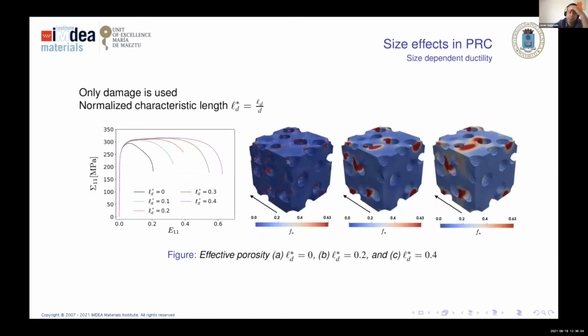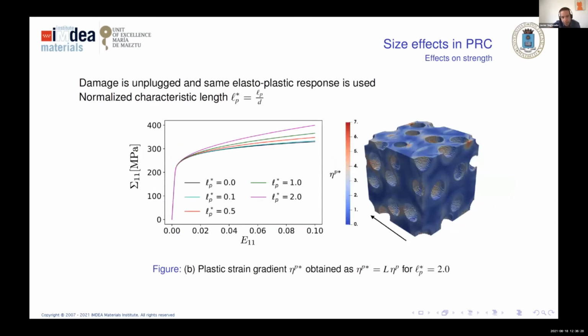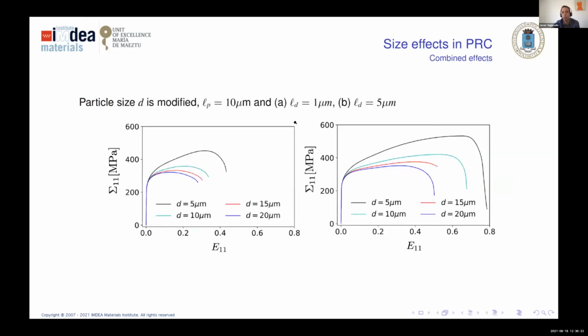I have almost no time to finish, just showing that if we combine strain gradient plasticity with damage, we can observe the size effect. The first one in damage is that the smaller the particle, the more ductile. We see that the curves move to the right, and in the case of the strength, the smaller, the stronger. And if we combine both, we can see which are the optimal particle sizes for particle reinforced composites.